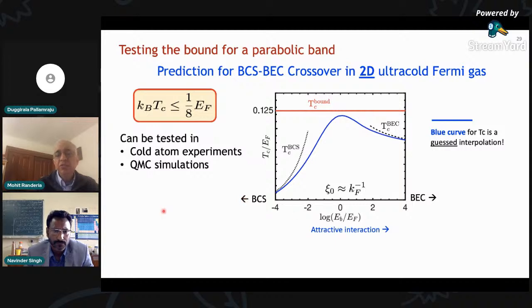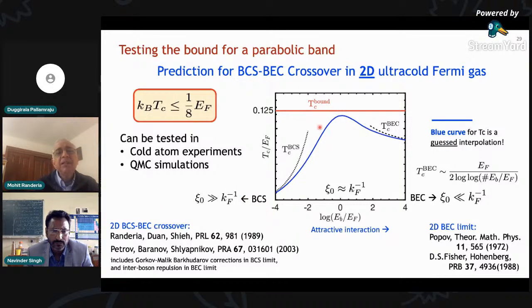And here, what I've shown you is we know what's happening in the BCS limit. We know what's happening in the BEC limit. You can think of the x-axis as increasing attractive interaction, very weak attractive interactions to the left, very strong attractive interactions to the right. You go from very large BCS pairs all the way to tightly bound point bosons with BEC. So of course, in the BCS limit, as you increase the attraction, TC goes up. But in the BEC limit, actually in 2 dimensions, there is no Bose-Einstein condensation. So if you go to non-interacting bosons, TC must go down to 0.